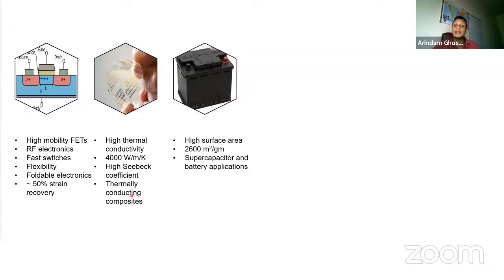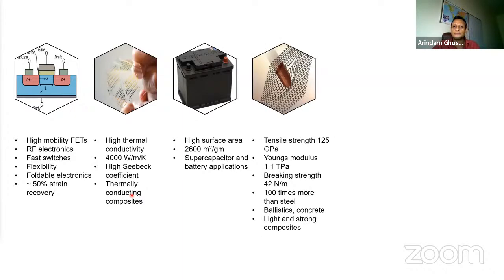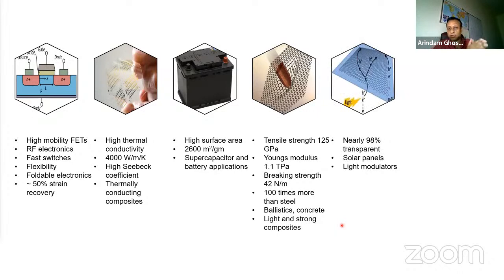Then you can have a very large surface area of nearly 2,600 square meters per gram of graphene, and it is highly conductive. It has a very interesting application in supercapacitors, in car batteries, for example, and many such battery and energy storage applications. Because of the unique mechanical property also, graphene has a breaking strength of 42 newtons per meter, which is nearly 100 times larger than the equivalent thickness of steel. So it can be used in very strong applications in ballistics, in concrete, for example, and in light and strong composites. We have nearly 98% transparency, so you can use it in a solar panel, in light modulators, and